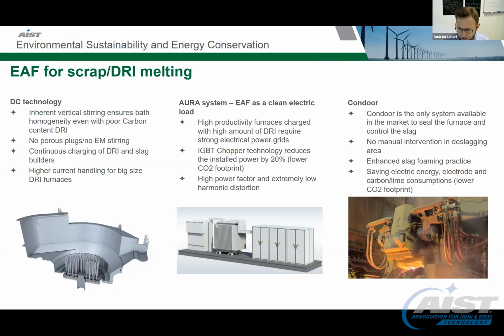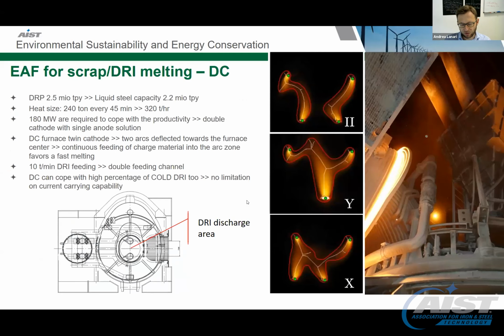Third point is a little bit more detailed one. Everybody's aware that when we are handling DRI inside the furnace, there's a lot of generation of slag. So a lot of energy is going to be lost in the slag, not only energy, but also some rich material like lime addition, carbon, which has no time to react in the furnace, but will be lost. So one key point is to handle the slag in the proper way. So we will spend some 4 more minutes on each of these main items, just to give you a little bit of our inside view on the future of the electric arc furnace for DRI.